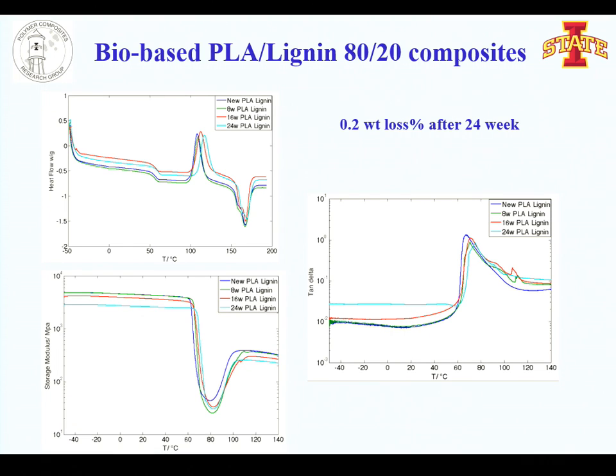How brittle is this when you start out? This material is a little bit brittle. Will it crack easily? The reason I'm asking is that when we're mechanically running these two machines to be potted, if you have too brittle a piece of plastic, it's going to crack just like that. It's like having potato chips all over the inside. Not with this low concentration of lignin. If we increase it more, it will be more brittle. Because what's on the end here is fairly brittle, and you can crack it just like that. In a lot of plastic pots, that's the biggest concern we have, and exposure to sunlight too has caused them to become brittle. I'm just asking because I don't know.